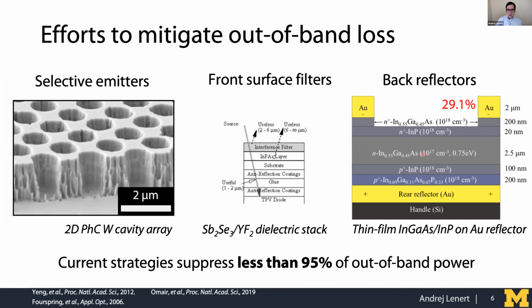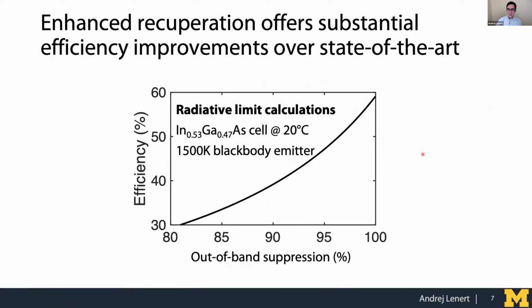However, looking at what's been done so far, what we see is that current strategies only suppress about 95% or less of this out-of-band power. And you may say that seems pretty good, but actually if we look at the sensitivity to this metric, what we see is that in the radiative limit and at these prototypical conditions, by improving the reflectance by a few percentage points, we can reach very high efficiencies. So at 95% reflectance, we're bound to 47% efficiency, but if we go to 100, we max out at 60% efficiency. And so these are large gains for marginal changes in out-of-band reflectance, so a key metric to improve upon.